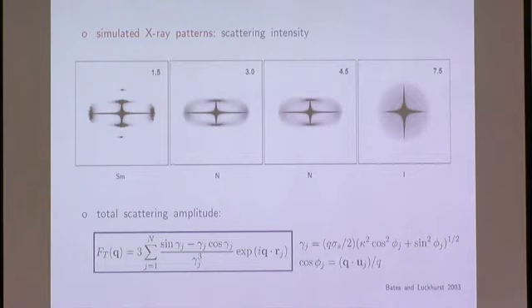So in this calculation, we assume that we're dealing with ellipsoidal scatterers, and then following a procedure also followed by Bates and Luckhurst several years ago, we ended up with these patterns here. What we are looking at here is basically a two-dimensional Fourier transform of the density of the system. This is a smectic temperature, these two are nematic, and this one corresponds to an isotropic state point.